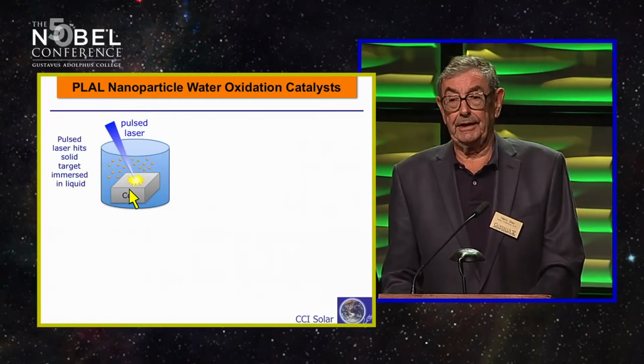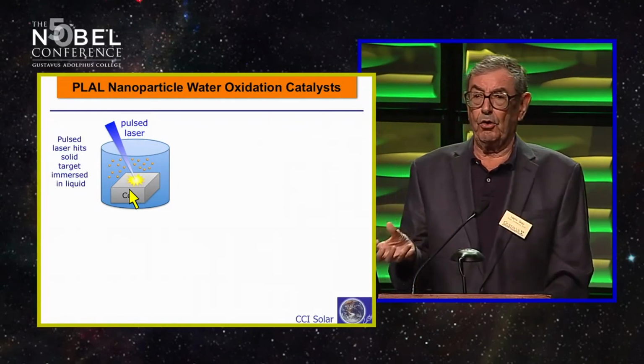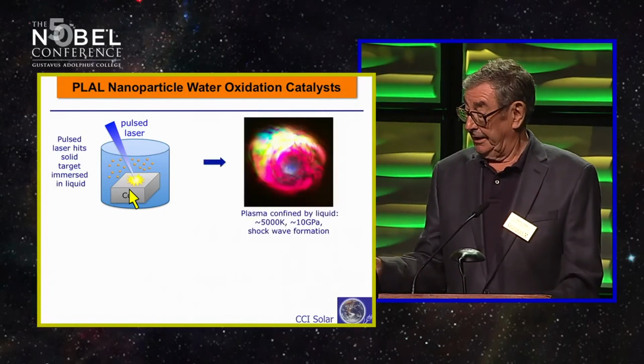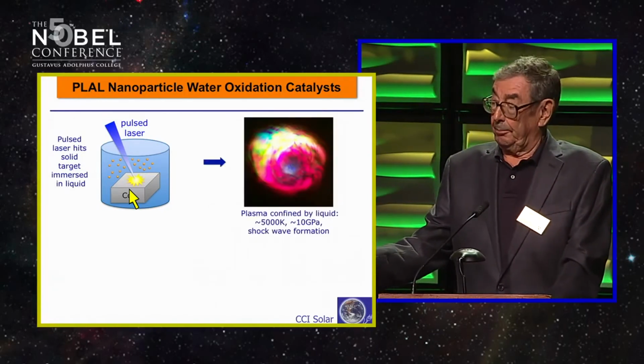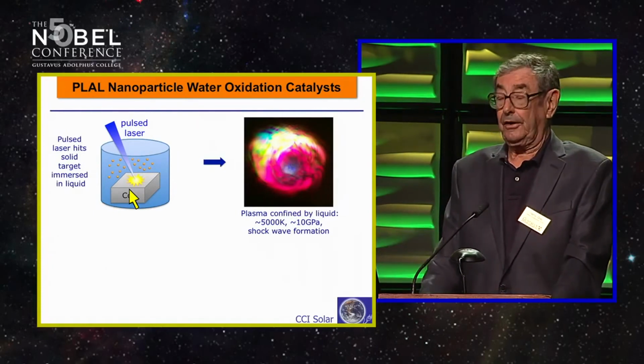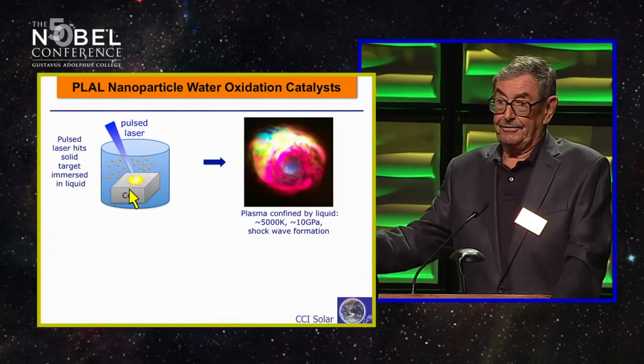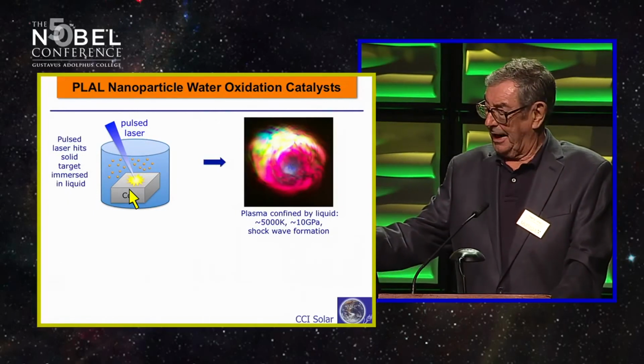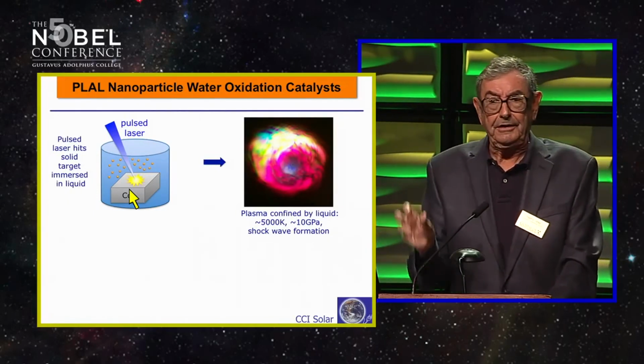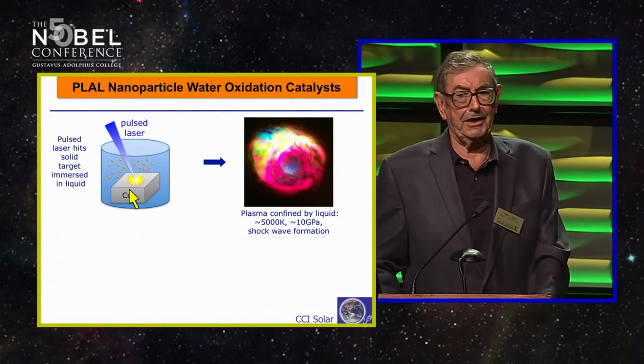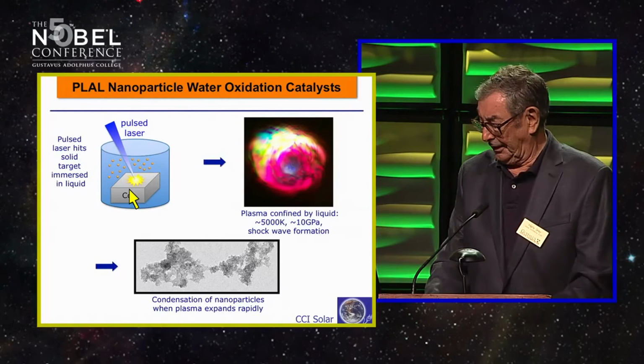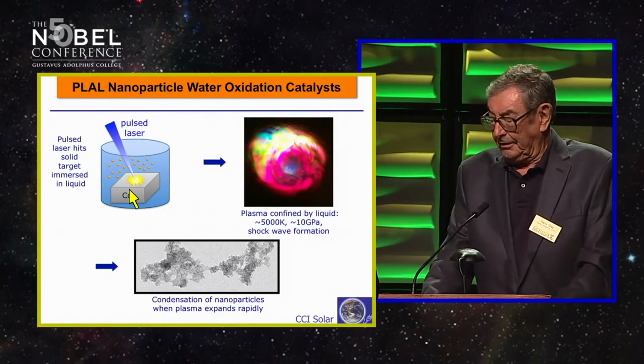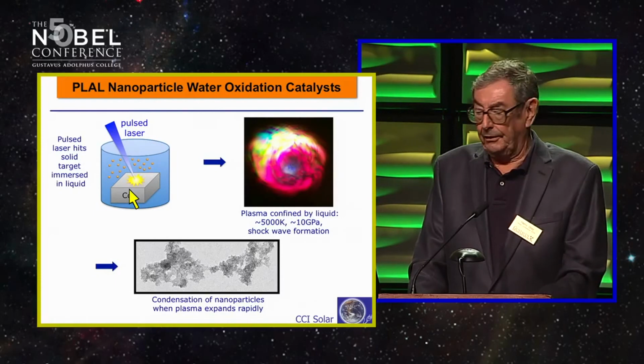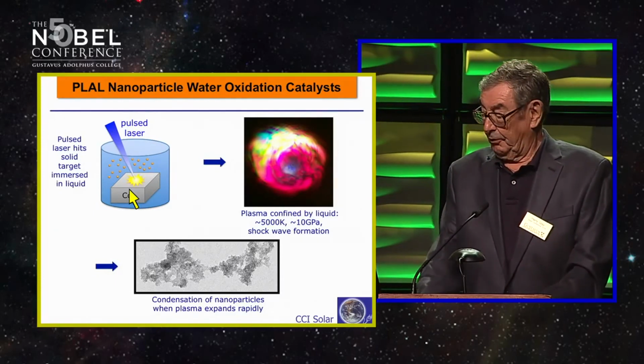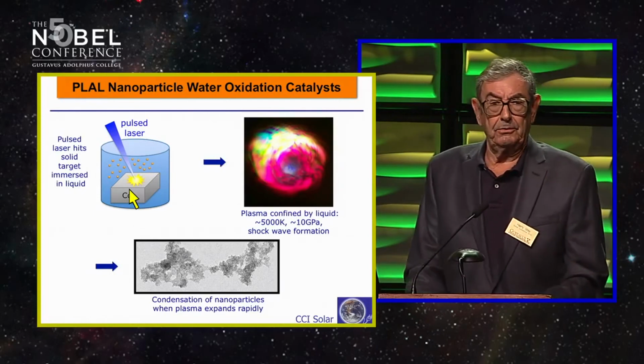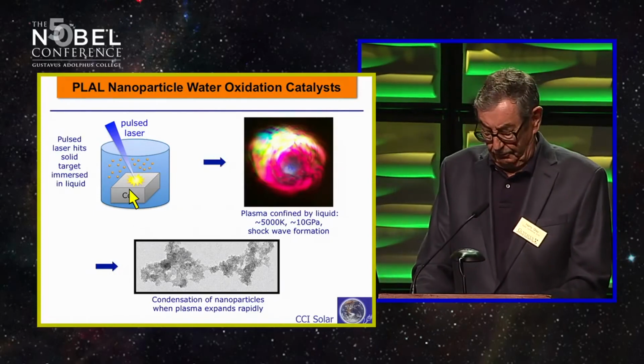with a pulse laser and literally explode the target because it has enormous energy, so we basically explode it into a plasma. We generate a plasma out of this laser targeting, a plasma at 5,000 to 10,000 degrees Kelvin under high pressure with all the components that the kids out there have told us we ought to have a look at. These systems then cool into beautiful nanoparticle materials, quantum confined, in which we can vary the size of the nanoparticle with the laser pulse energy and the laser pulse width.